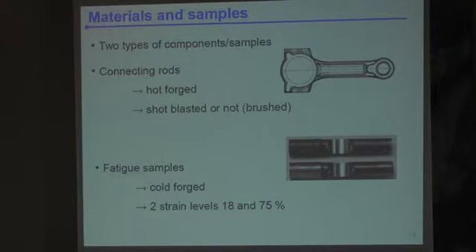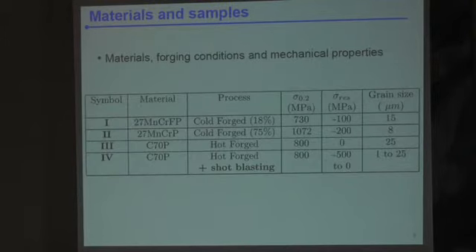Other samples have been extracted from extruded bars with two different strain levels, 18 and 75%. So they're extruded, and then you extract the sample from the skin of those bars. So this is a summary of the materials.